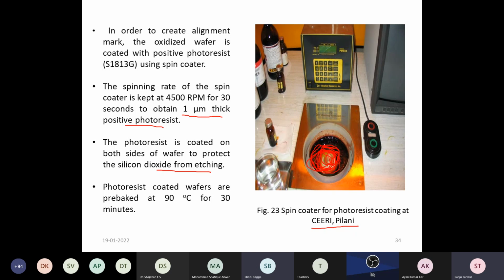Then, as you know, lithography has certain steps. This photoresist coated wafer is pre-baked at 90 degree centigrade for 30 minutes. What is the benefit of pre-baking? The photoresist properly adheres to the substrate, to the silicon dioxide we deposited, and becomes a bit hard.